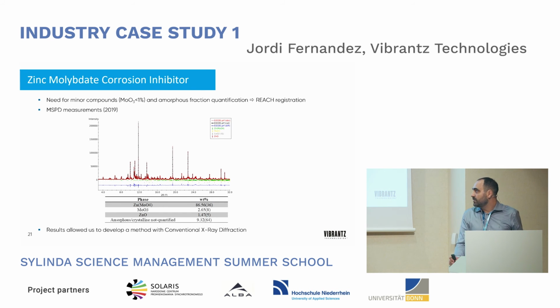Again, the results allowed us to also develop a combined method, because it is quite difficult for the industry to use synchrotron techniques as a daily test, and many times you have to certify a lot of industrial lots to be sold in Europe. But we were able at this moment to run a conventional X-ray diffraction test and to do some calibration of this conventional X-ray diffraction test, thanks to the results obtained with the MSPD measurements.